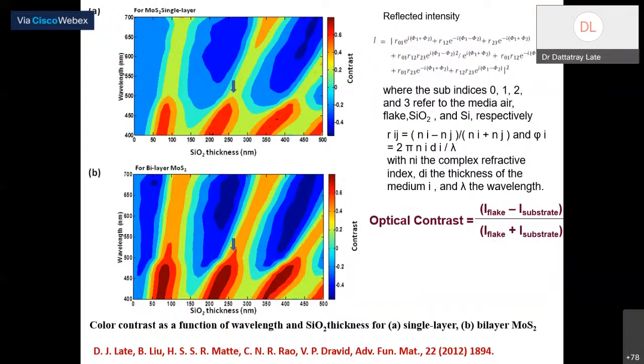Okay, so why is my optical contrast changing? Because of the change in SiO2 substrate. So you need to go back to the 12th standard equation of reflectivity intensity. Basically, you need the refractive index of the SiO2 substrate which you have taken. For example, we should know the refractive index of the medium, air, the refractive index of MoS2, the refractive index of the SiO2 substrate, and silicon. So this gives you a very simple equation, which relates the intensity of the flake minus the intensity of the substrate, divided by the intensity of the flake plus the intensity of the substrate. Once you put in all these parameters, you can calculate and you will get this particular color contrast. For example, you can see the left top image of SiO2 thickness as a function of wavelength.